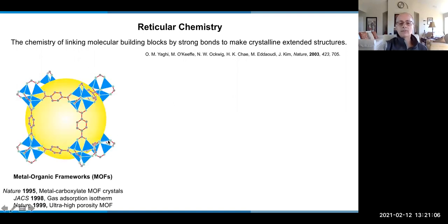And as I said, the result of this has been metal organic frameworks, which we showed in 1995 can be crystallized from metal ions and charged organic linkers. We also showed for the first time that they can be made porous by measuring their gas adsorption isotherm, and later showed that in fact we can make materials that have record porosity or ultra high porosity. I will not talk about MOFs, but leave this topic and just say that it's an established branch of chemistry now, and it has gone from basic science all the way to applications and commercialization.